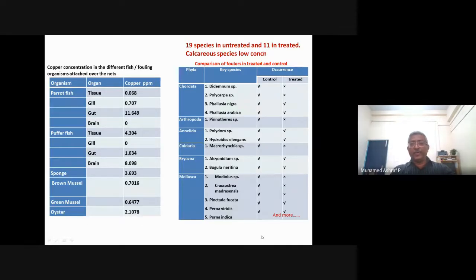And also we have seen what species of biofoulers are attached over the net. We found that in comparison, 19 species were found in the untreated net and 11 were in the treated nets. And one of the major observations was that calcareous foulers were comparatively less in the treated one. And these are all the other organisms we found in the net. There were parrot fishes and puffer fishes that had entered the net cages, and we took them out while removing the cage. These concentrations are within the standard or prescribed limit. We did not find any extra.